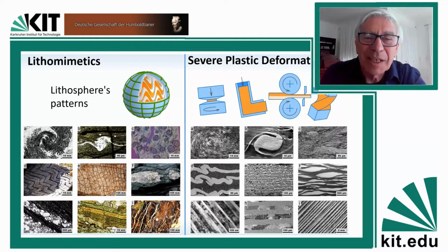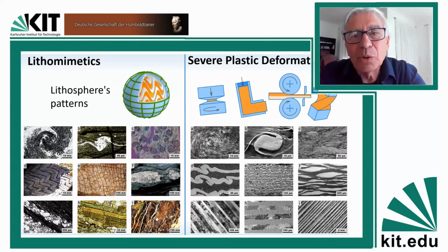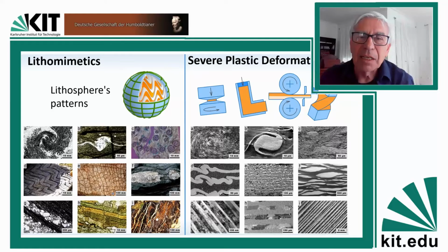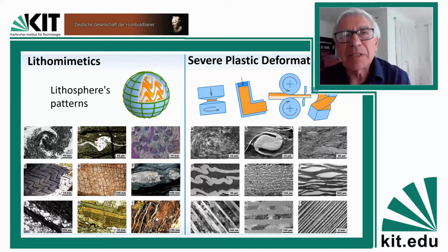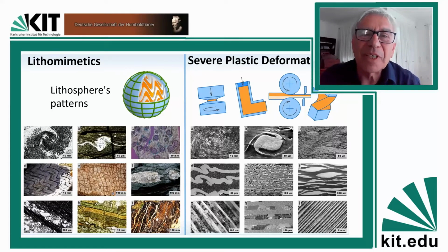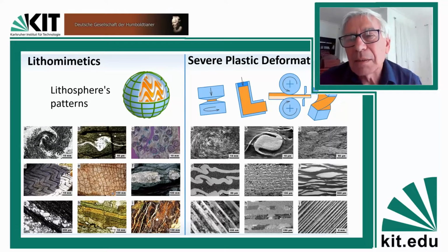You can produce huge strains of hundreds and thousands, not hundreds and thousands of percent, but really hundreds to thousands. So you can really, by this rotation, by this shear deformation that you produce, you accumulate a huge strain, and with this strain, you break down the microstructure of this material down to sub-micron scale and quite often to nanoscale. That means that you have a bulk material with very fine granularity, with very small nanoscale grain size. That provides the material with very high strength. You know, most of you would know that the strength of the material scales as the inverse square root of the grain size. And the grain size here being so small, you get a huge mechanical strength of the material.